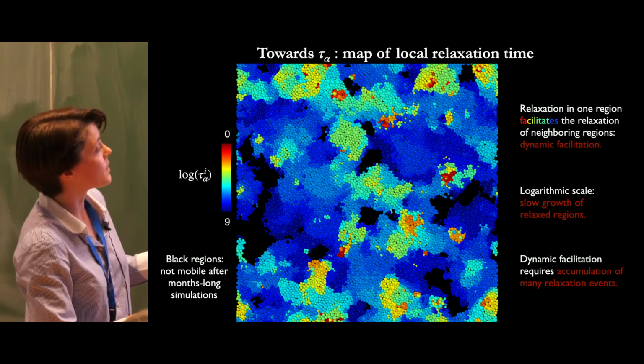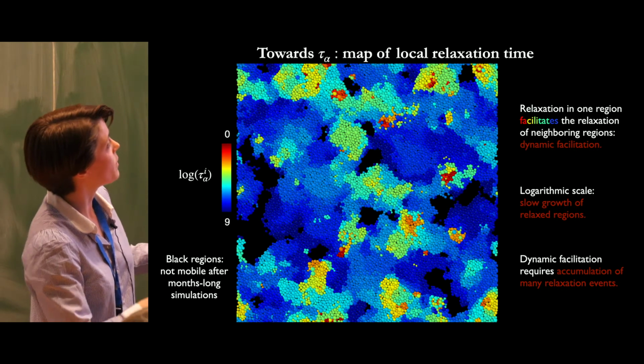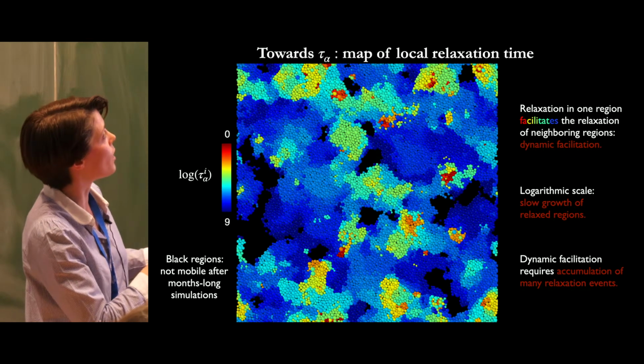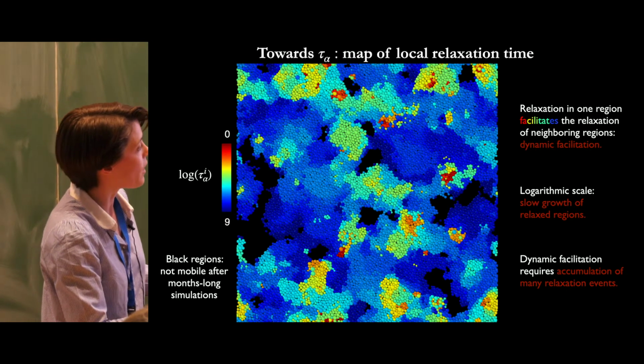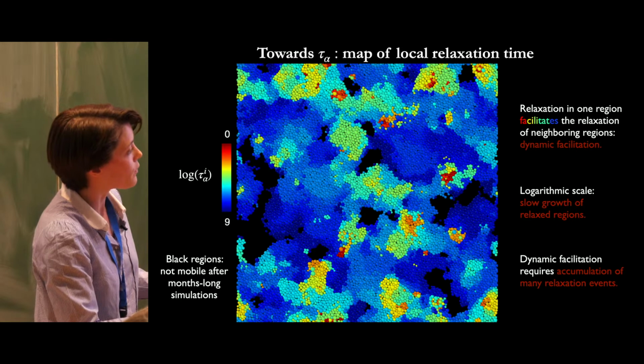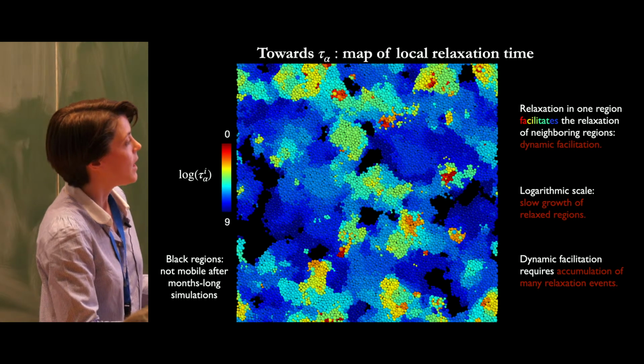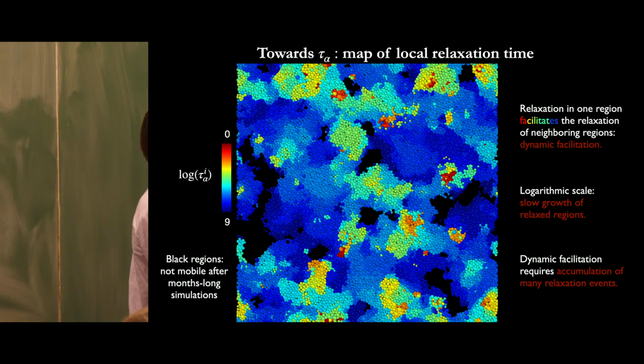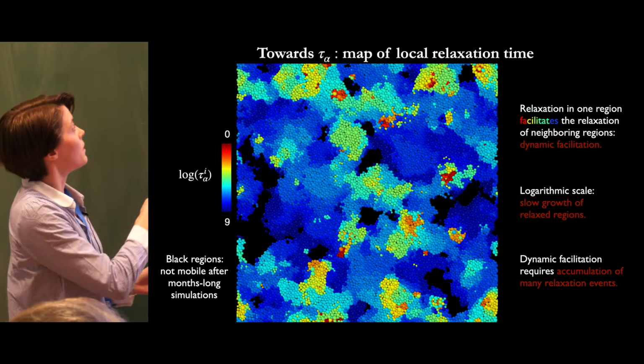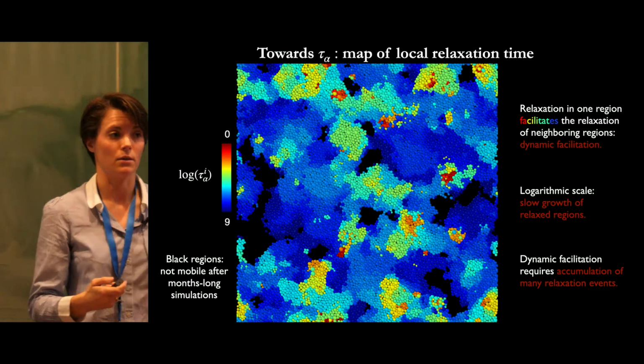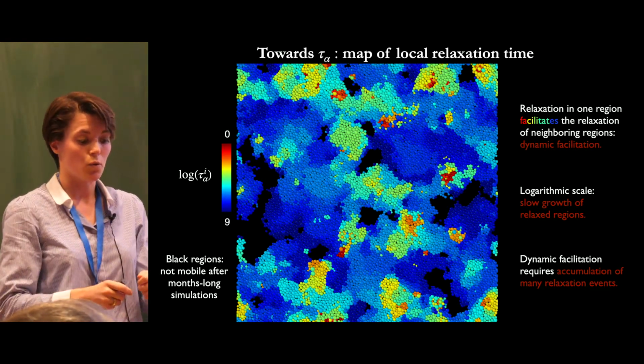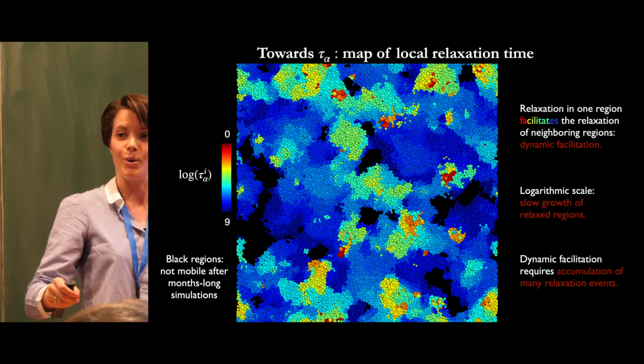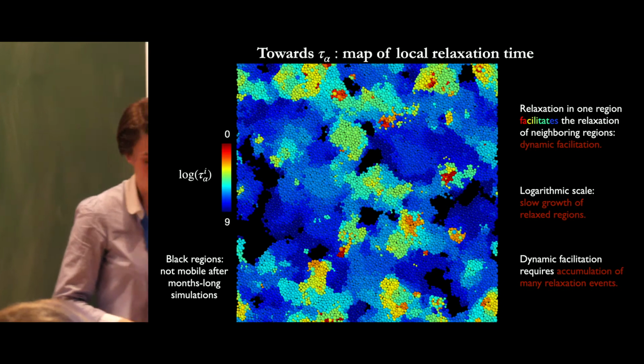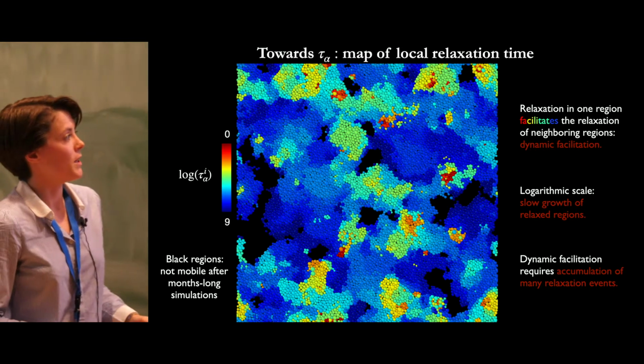Then in this structure, you can read this color code from red to blue. For example, here you have some particles that move early, and then you have a continuous color code going to dark blues. What that means is that the particles here that moved very early in time helped the relaxation of the neighboring region at later time. And this is the dynamic facilitation idea that Olivier described: you need to relax in one region to be able to help the relaxation in neighboring regions.